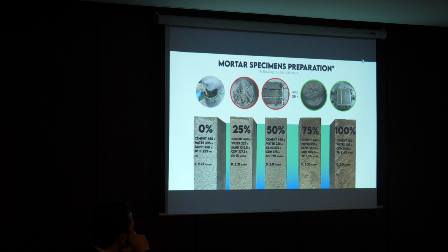During the mortar preparation, we had some problems with the workability, and that's why, as I said before, we used an additive, a super plasticizer, because it was practically impossible to cast the mix. In fact, there were also segregation episodes in some samples, and these samples were not taken into consideration because they were not perfect at all. There were some voids inside the molds and so on. That's why a super plasticizer was then used to work in the same workability environment for the mixes.